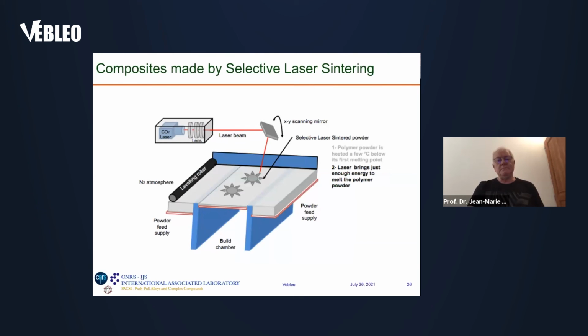This is a different experiment, which is the preparation of composite materials made of a blend between nylon and quasicrystalline powder, using a CO2 laser to locally melt the material to give the final shape of the material produced by additive manufacturing. And this is essentially infrared light.